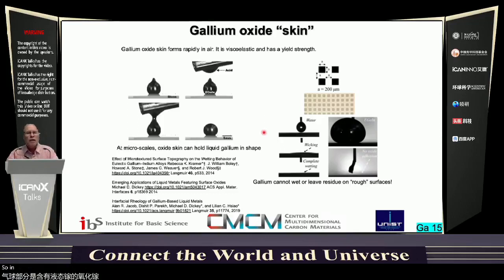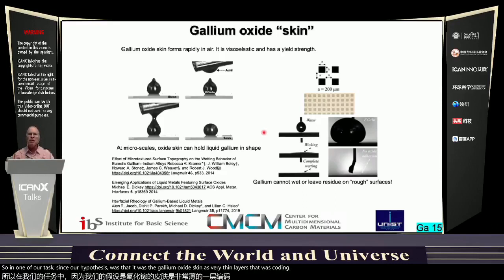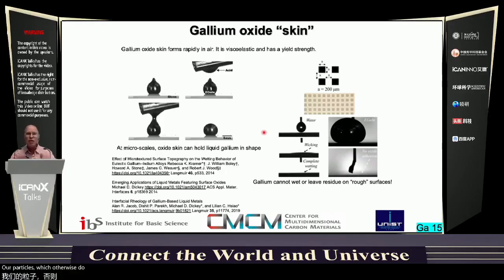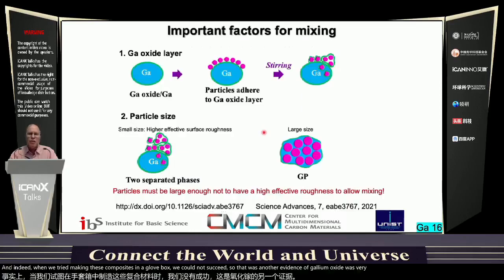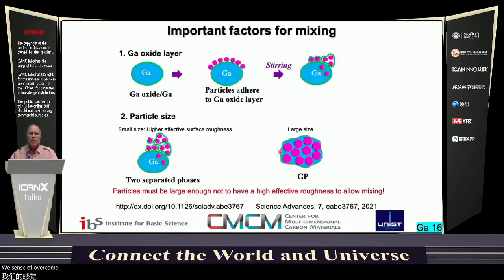So in one of our tests, since our hypothesis was that it was the gallium oxide skin, as very thin layers, that was coating our particles, which otherwise diamond and graphite would not be wetted by gallium itself, and that was allowing us to mix those particles in to make these composites. And indeed, when we tried making these composites in a glove box, we could not succeed. So that was another evidence that the gallium oxide was very important. We since have overcome this issue, and we'll be describing that in a future paper.